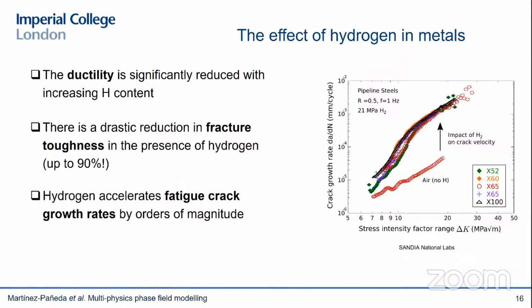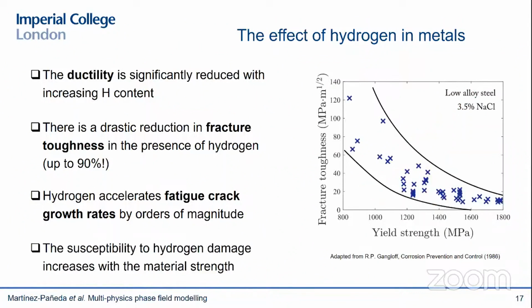And all the results I've shown so far are for mid-strength steels. But in high-strength steels, this susceptibility to hydrogen damage increases dramatically. So you can get fracture resistance reductions of orders of magnitude in these high-strength steels. And this is a key point to emphasize. The susceptibility to hydrogen damage increases with the material strength. You can see here fracture toughness versus yield strength, and you can see that these very high strength steels have a fracture toughness in the presence of hydrogen that is below 10 megapascals root meter, so almost as brittle as a ceramic.